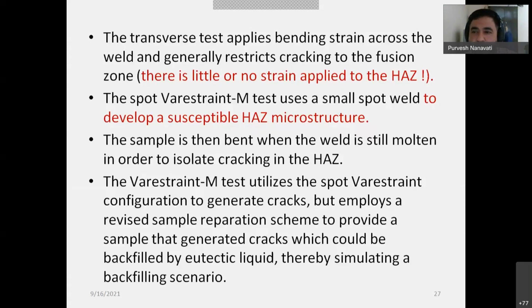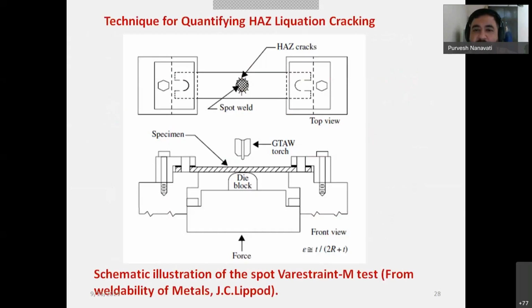So it's a modification to the original test where you would see only a spot weld. This spot will develop a spot weld, and this small spot weld develops a susceptible HAZ microstructure. So you will simulate a heat affected zone using a spot weld, and this spot weld will have an HAZ microstructure. Now, the test setup is something like this. You would see in the picture that instead of making a weld on the line, only and only the weld is made on the spot.